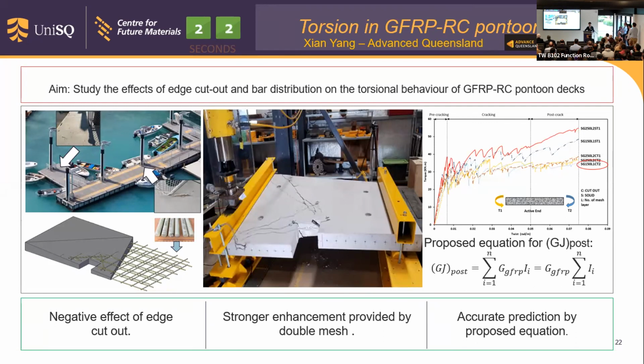An experimental study was conducted in my research. The generated torque twist curve on the right side shows the negative effect of the edge cutout on the torsional behavior. But 2 layers of GFRP mesh reinforcement distribution can enhance them. Additionally, an equation was proposed to estimate the post-cracking torsional behavior by considering the contribution of the bar distribution.